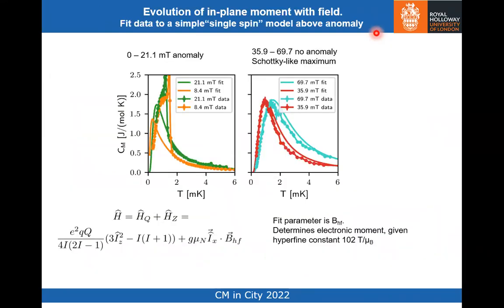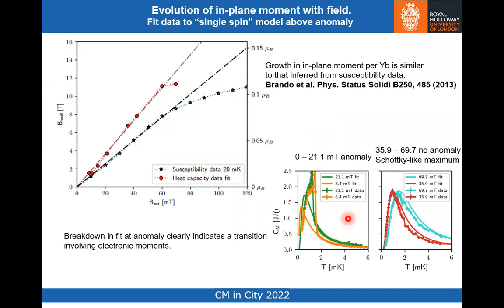Okay, so what we see in more detail then is over this field range, we see this anomaly, and what we can do is fit the data at temperatures above the anomaly, and the fit parameter there is the hyperfine field, which determines the electronic moment given the accepted value of the hyperfine constant. At these larger magnetic fields, we see no anomaly, and we can fit the data over more or less the whole temperature range to determine this hyperfine field. And when we do that as a function of in-plane field, that's the hyperfine field as a function of in-plane field, and here is the size of the electronic moment as inferred from that hyperfine field.